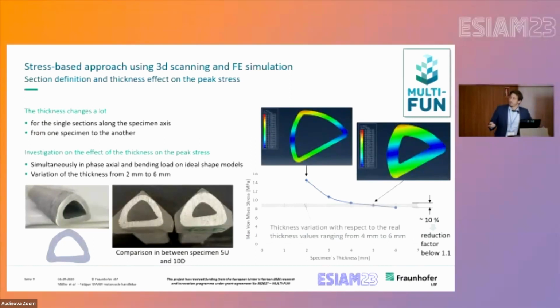And what we see is that, from a maximum von Mises stress, in this case from the simulation, at a lower thickness the stresses are higher, and they decrease with increasing thickness. In the range of our application, between 4 to 6 millimeters, the difference in maximum von Mises stresses is around 10%, so that we could use a reduction factor, which is around 1.1 in this case.